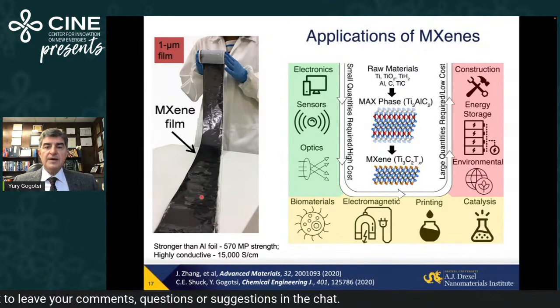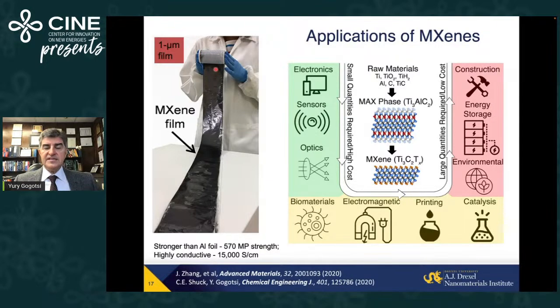What is also important, processing is simple. We take this colloidal solution of two-dimensional flakes in water, no binder, nothing needed here. And we can basically simply spread it by doctor blading over a surface, dry it, and we get this film. This is, for example, a 1 micron thick freestanding film of MXene that can be made. It's now on a tape, but again, can be separated. And you can see here all these bubbles forming as it separates from the tape. It gets strength like aluminum foil and has high conductivity. Again, just colloidal solution in water, spread, dry, you get a film.